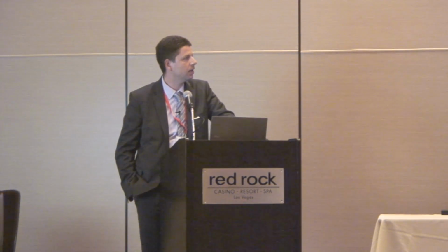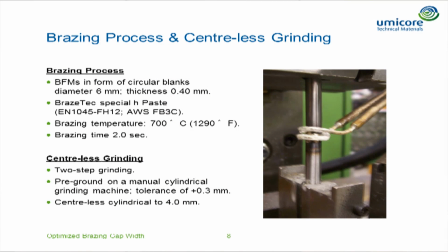The colleagues of AKA made the brazing tests, and in between they used different kinds of brazing filler metals with a diameter of 6 millimeter and a thickness of 0.4 millimeter. They used a flux which was applied on both sides, the brazing temperature was set, and the brazing time was set to 2 seconds. They had a special fixture which allows to set the brazing gap afterwards.